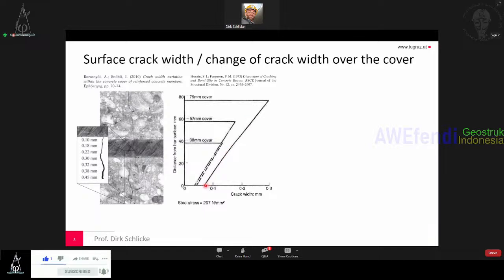measurements over the concrete cover. And you see here, for example, distance from bar surface 0 to 75 millimeter cover. The increase here is linear, but I guess they have only two measurements over the height, so they made it linear. They show that the crack width increases linearly over the height. As you can see here, it's the same. Right, so from 0.1 to 0.45, here it increases from 0.05 to, for example, 0.15, and so on, for a given steel stress.